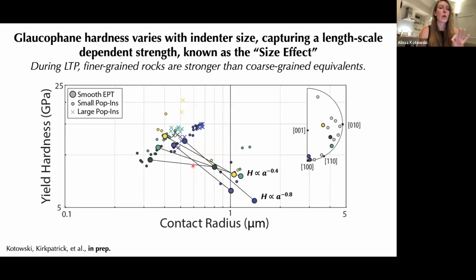The bold circles here show you the best estimates on true yield hardness for these grain orientations, and the smaller circles are pop-ins with relatively small measurable displacements, and the X's are much larger displacements. This is a phenomenon that's also very well documented in the materials literature, which is smaller is stronger. And this is thought to reflect the role of strain gradients and dislocations in modifying plastic behavior. So basically, for identical strains of a single crystal, a smaller volume of the crystal will have higher dislocation density, and that makes it harder.